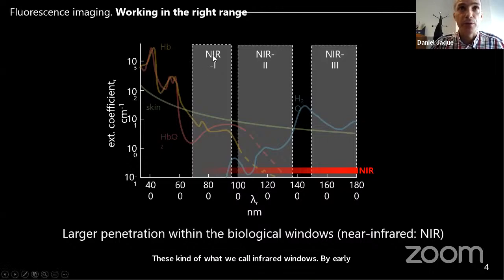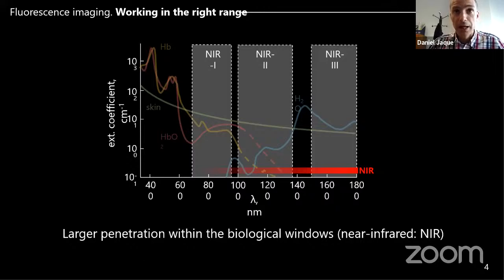There is near infrared window 1, near infrared window 2, and near infrared window 3. The first one goes from 700 to 980 nanometers. The second biological window is from 1 to 1.4 microns, and the third biological window is from 1.5 up to 1.8 microns. What happens in this spectral range? In this spectral range, the light can propagate through the tissues, and you can use that to obtain an image of internal organs, for example.